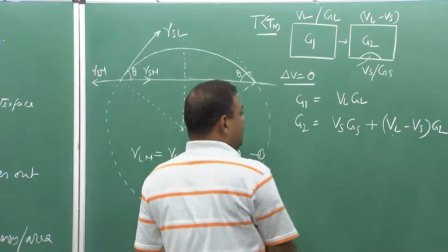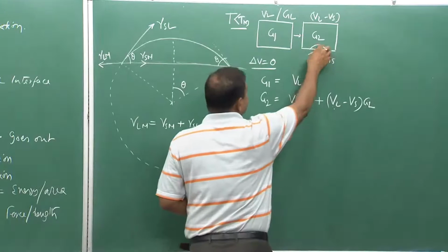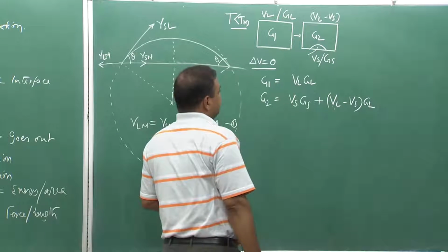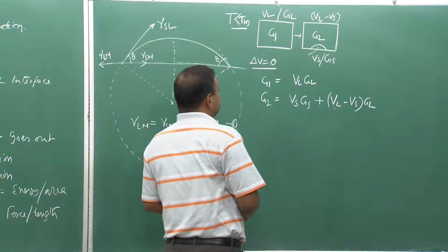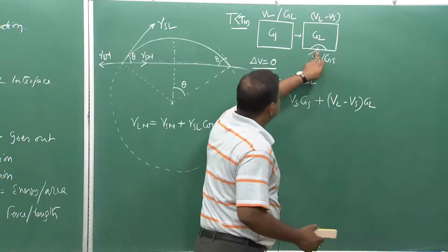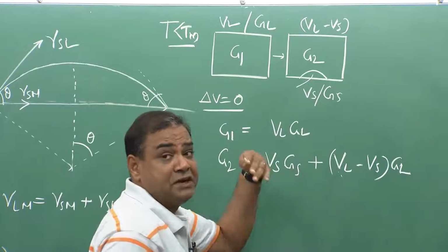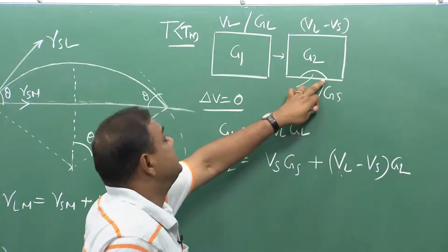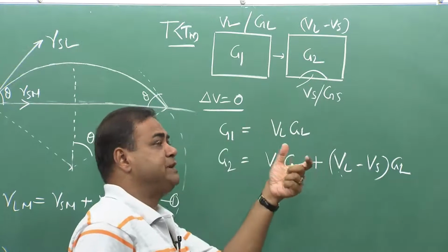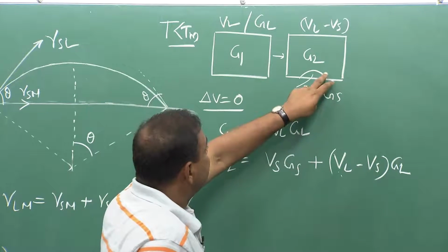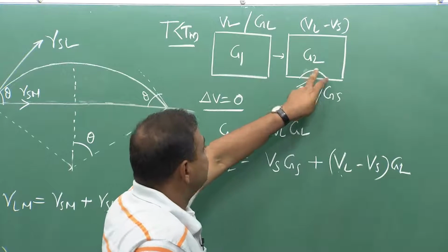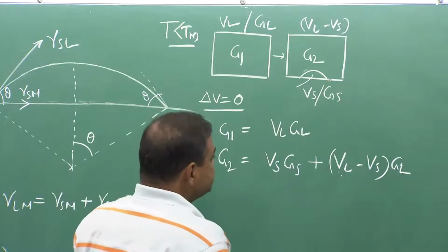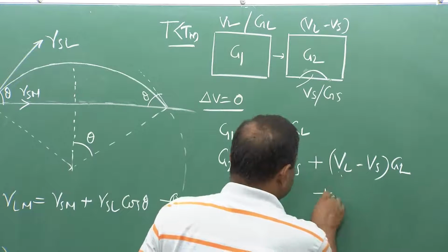Now, it does not stop here. We have already created interfaces. Initially the interface was liquid mold, which is getting replaced with the solid mold interface. That means one part would be negative, and we are creating one more interface, which is this one. So, there would be two interface contributions.